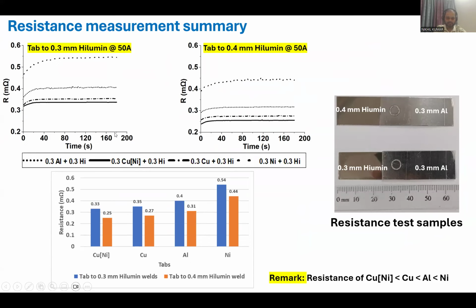So this is captured for 180 seconds. For 3 minutes, I have passed the current of 50 amps and captured the resistance. This is a constant passing current. So as you have seen, there is a spike of resistance, but after a certain period of time, there is a constant resistance. There is not that much spike in the resistance, because after some time, the heat dissipation and heat generation are nearly the same.